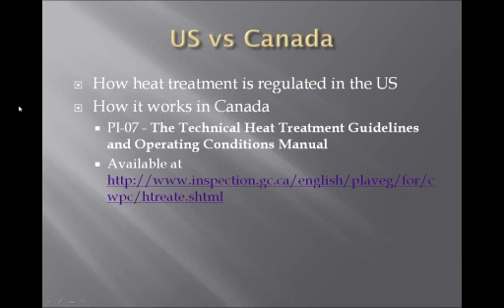So I've covered a little bit here on the U.S. versus Canada. Heat treating in the U.S. is run and regulated a little bit differently than Canada, and therefore some of the kilns available out there may not be tailored for Canadian operations. In the U.S., as mentioned, 3 core probes are plugged into the product throughout the chamber. They're monitored. They hit 56 degrees Celsius. They're held for 30 minutes, and your charge is complete. Therefore, you can hear of different kilns cycling in an hour to an hour and a half and meeting ISPM 15 criteria. In the U.S., the ALSC, or the American Lumber Standards Committee, oversees the heat treatment.